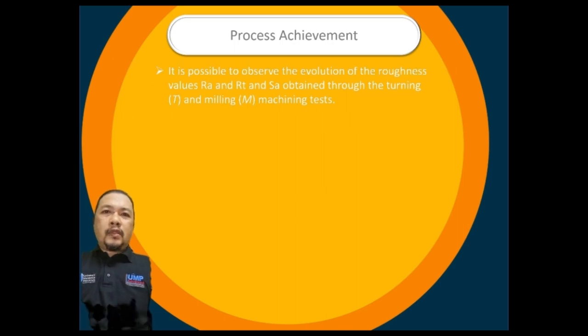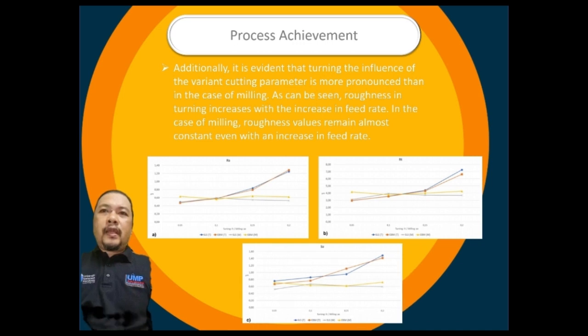It is possible to observe the evolution of the roughness values RA, RT, and SA obtained through the turning and milling machine tests. Additionally, it is evident that in turning, the influence of the varying cutting parameters is more pronounced than in the case of milling. As can be seen, roughness in turning increases with the increase in feed rate. In the case of milling, roughness values remain almost constant even with an increase in feed rate.